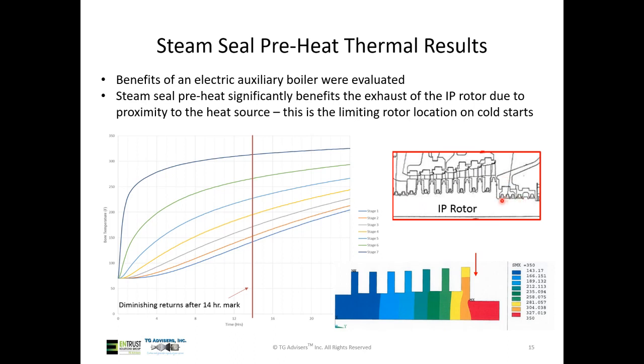Well, if I can put those steam seals on in advance, it's essentially putting some heat to the back end of the rotor. And that's going to start to conduct through and give you some heating benefit from the back end first, which is the part that heats the slowest when I actually start rolling up the unit. So it's a good way to cheat and get some free heating in advance of actually rolling. So what we're showing over here is just some modeling, and the biggest benefit is at stage 7, the back end. Limited benefit kind of up front, but that's okay because that's going to heat the quickest once we actually admit steam to the unit. So if you're on a day ahead market, you have an aux source of steam, go ahead and put the steam seals on. Typically 350 to 400 degrees Fahrenheit is kind of the temperature range that we see, but we've seen lower, we've seen higher.